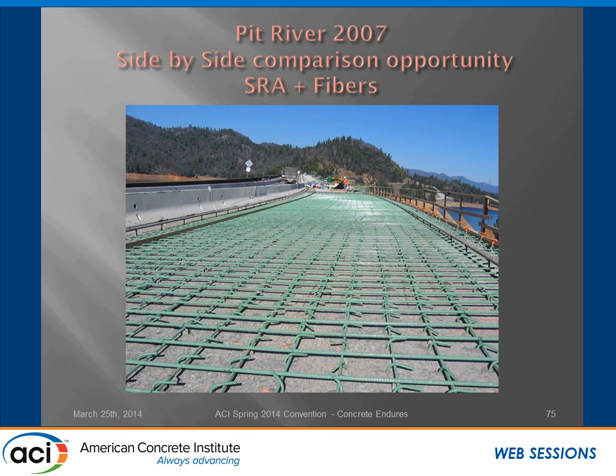The deck concept here on portions of that bridge, we were able to replace the entire deck. In certain areas, we could only take off a little bit of deck and put another riding surface on it for stability purposes. These are number fives married up with number sevens. That's an inch and a half worth of steel. Add some clearance, inch and a half clearance to that cover, and you don't have a whole lot of room for concrete to work underneath there. As Rick pointed out, these are the typical jobs that are ripe for drying shrinkage cracks. You're really restrained on the bottom, and we see cracks on these type of fixes all the time.